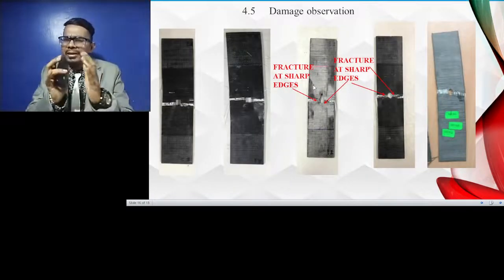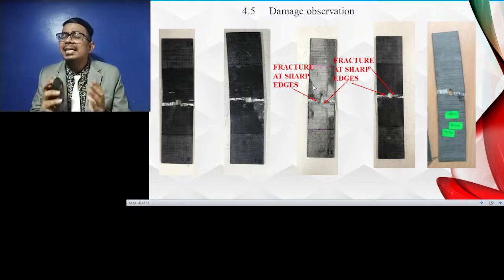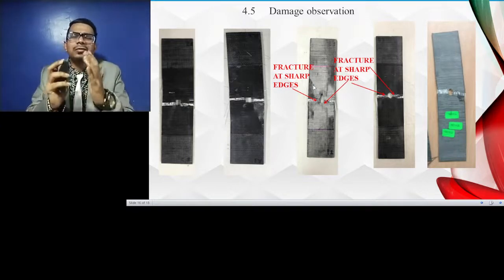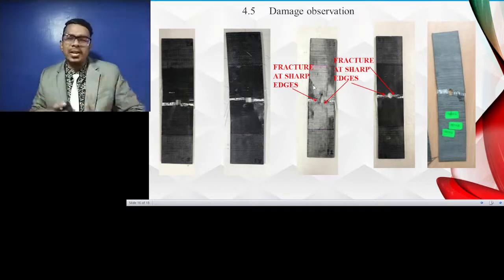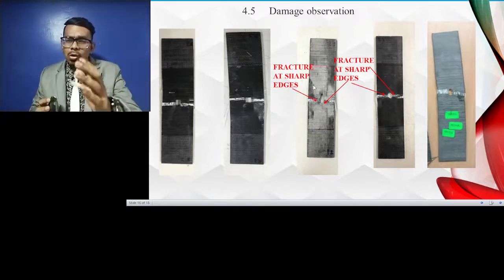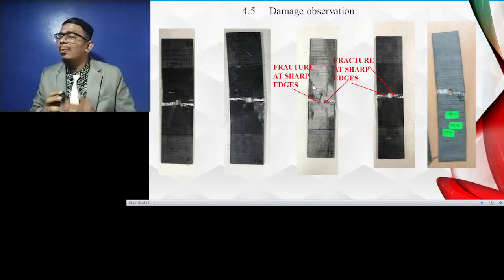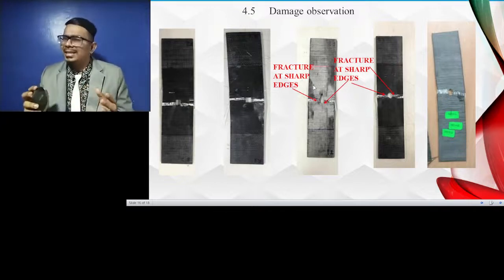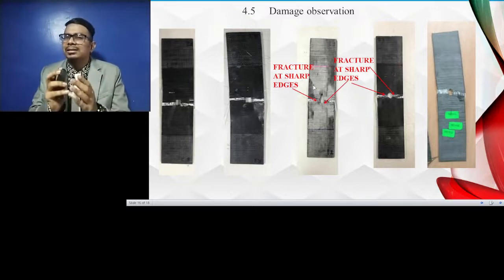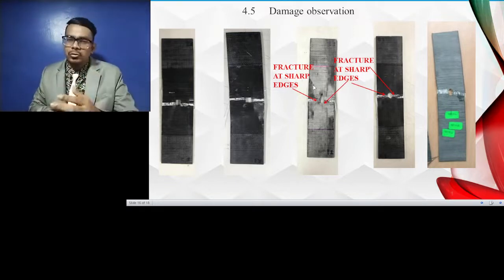Moreover, based on damage observations, the brittleness characteristics of the glass fiber lead to the specimen's failure. Based on the findings, the holes which have sharp edges fractured first compared with those with normal edges, and we can also say that fractures occur at the sharp edges of the holes.